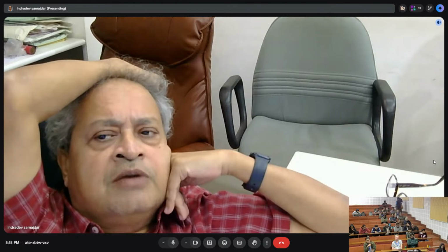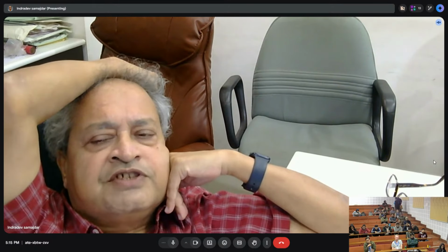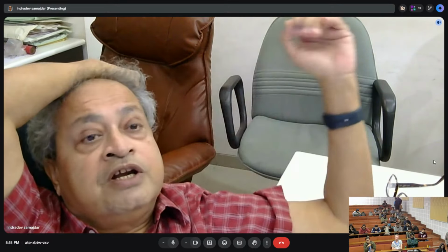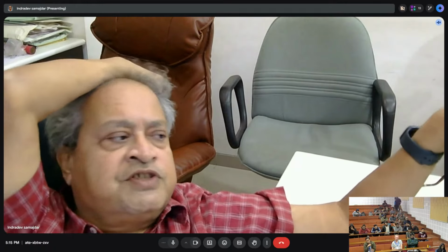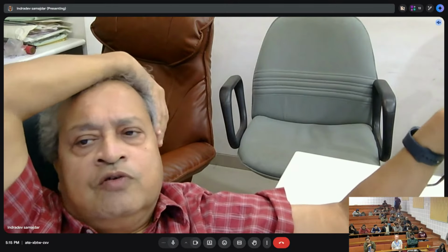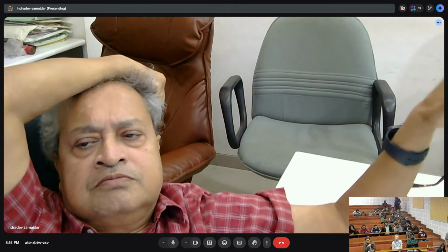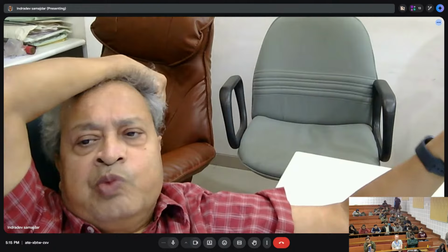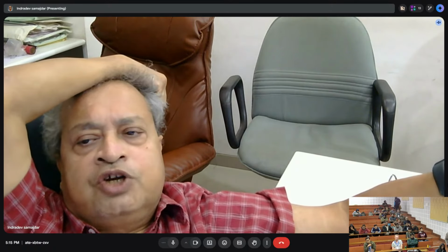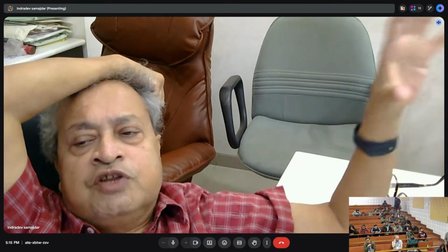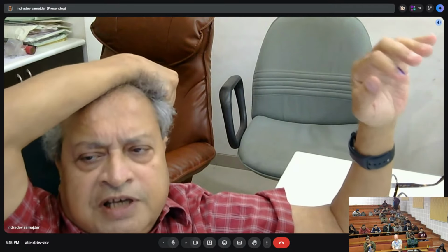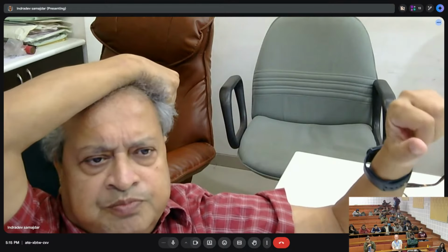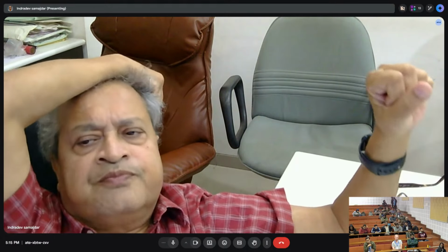So a laboratory guy, those high-res guys, the physics guys, they would prefer using a double bounce monochromator. Our physics is buying a new machine. I was involved. So this is the right thing to do. But your intensity will go for a toss. So this is on the incident side. I prefer using lens because most of our work is point focus.